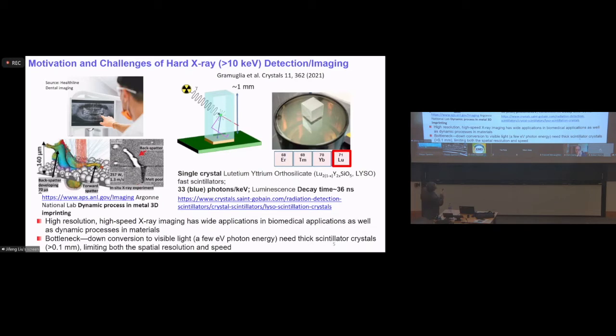For example, if you have an X-ray source coming here, it supposedly should hit this pixel. But now you're generating on average 33 photons randomly in this piece of crystal. So essentially that emission direction is really random. And essentially this causes the problem of reduced spatial resolution. And if you detect high energy X-ray, basically this needs to be thick, around 1 millimeter. So if your light source is higher, essentially the illumination area is bigger. So essentially you get a sacrifice in the spatial resolution here.